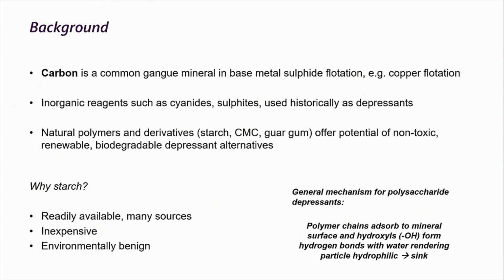In general, for the polysaccharides like guar gum and carboxymethylcellulose, the depressant mechanism is essentially that once it's adsorbed to the mineral surface, the excessive number of hydroxyl groups along the polymer chains will form hydrogen bonds with the water phase, render it hydrophilic and cause it to sink.